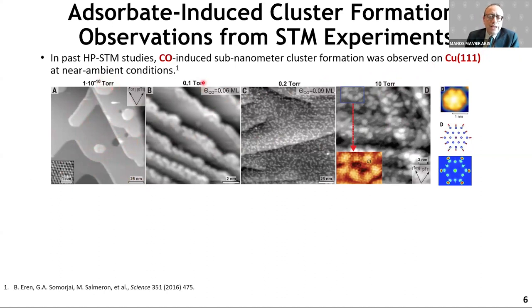Now, gradually they started letting some carbon monoxide in, 0.1 torr, 0.2 torr, up to 10 torr. And then they zoomed in their microscope and looked at the monatomic step edges separating terraces. And you can clearly see that even with this tiny amount of CO, you start seeing some corrugation on the step edges. If you then double the pressure of CO and you zoom out, go back to this length scale,